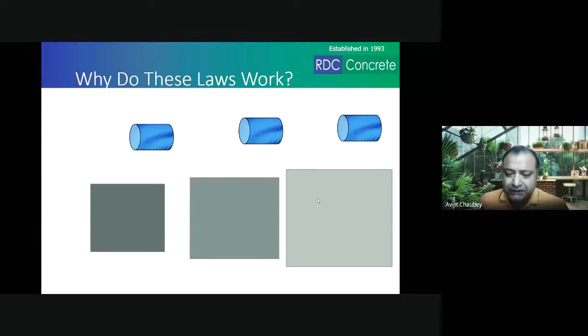And once this clay paste dries up, or when it starts developing the strength, it will start showing that the first mix is stiffer, and the third mix is weaker, because the water molecules between the clay particles evaporate out during the course of hardening. And these clay particles adjust themselves to incorporate even the water particles amongst them. And you get a very porous kind of a structure where the water evaporates.